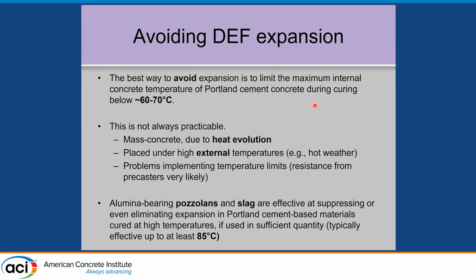High external temperatures too: some of the precasters in the Southwest US were casting at 50 degrees Celsius, and then in steel molds and outdoor exposures in the sun, so these concretes were getting baked. And that in part may have led to some problems. And sometimes there's problems in implementing temperature limits. I think people are much better now. This was 20 years ago. People are much better now with wireless sensors implementing temperature, thermal controls on concrete.